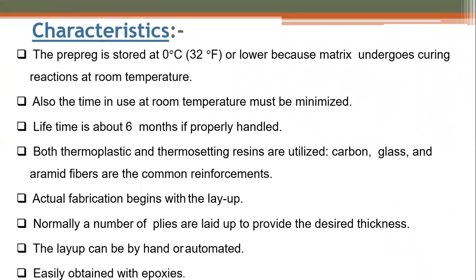Coming to the characteristics, generally the prepreg is stored at 0 degrees centigrade, in the solid state. That is 32 degrees Fahrenheit or lower, because the matrix undergoes curing reactions at room temperature. The matrix undergoes curing at room temperature, but it is not fully cured, only partially cured. So we put it at 0 degrees centigrade.